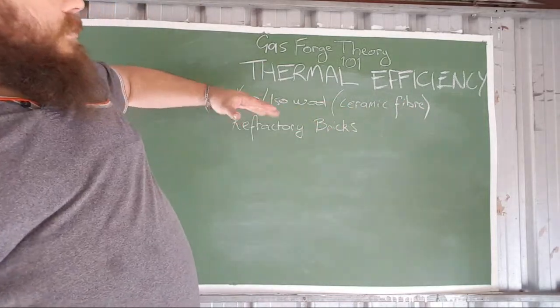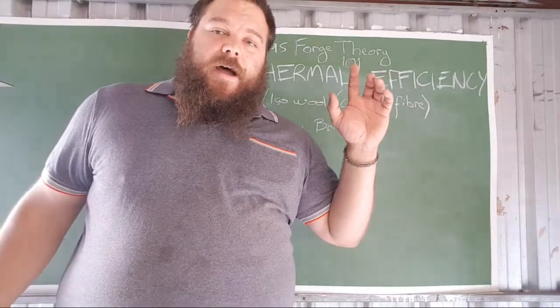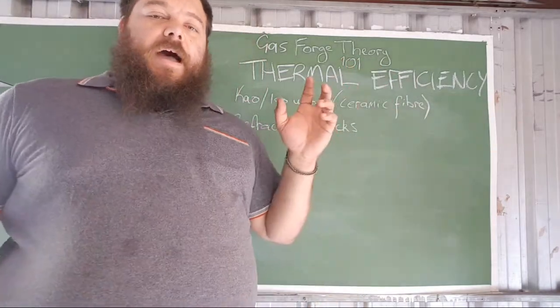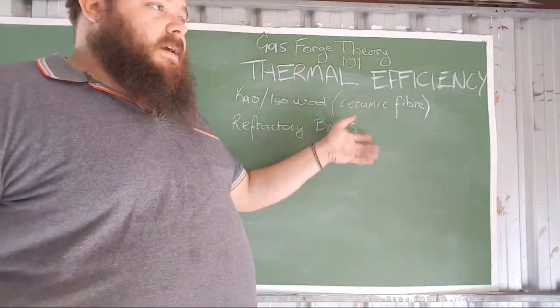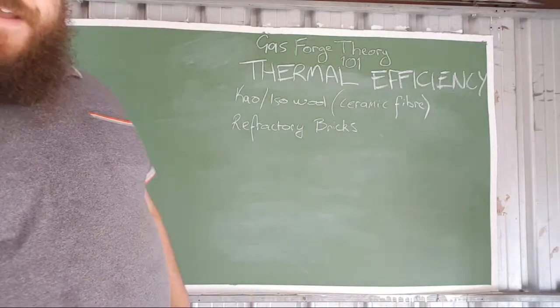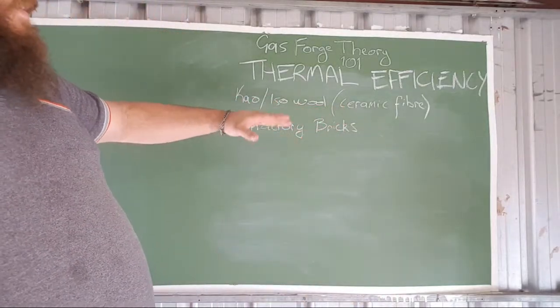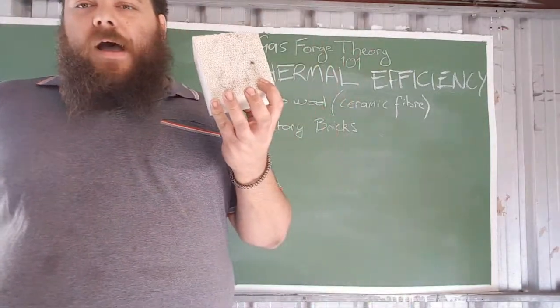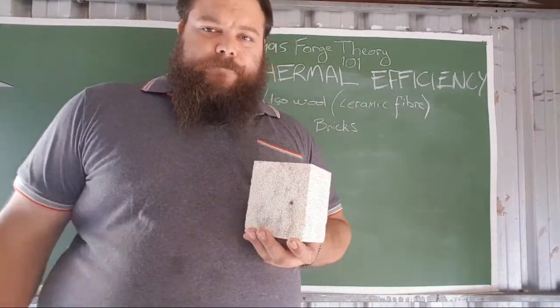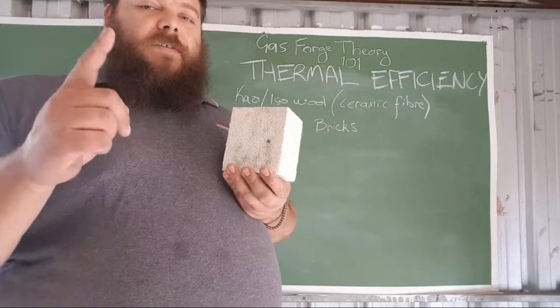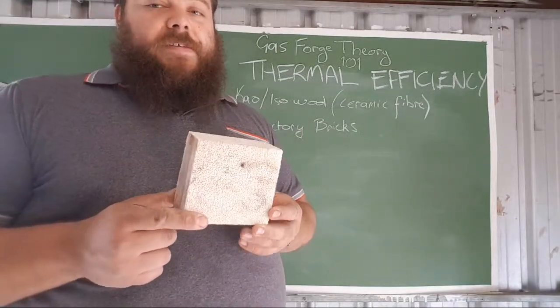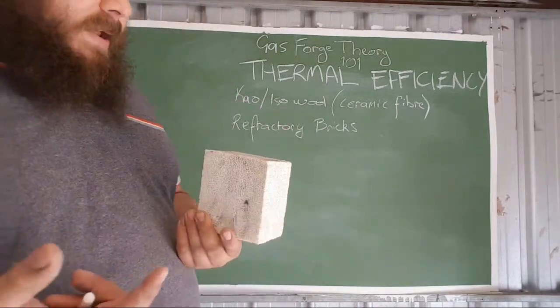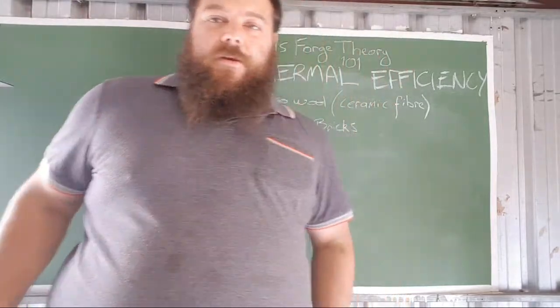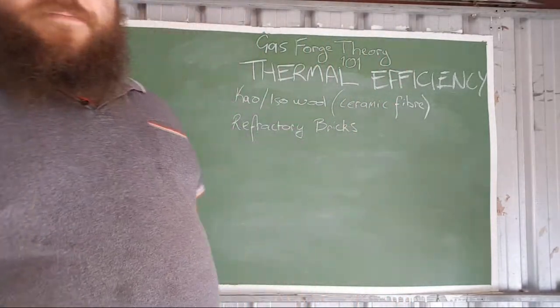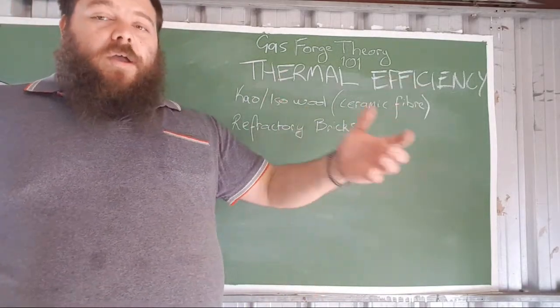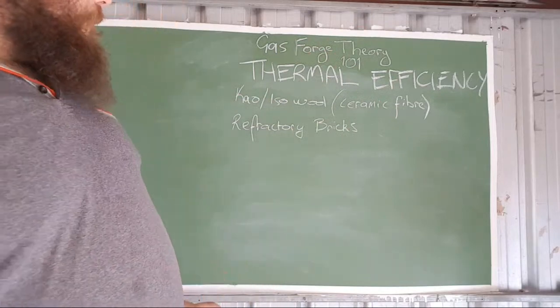So, both Kaowool or ceramic fiber blanket and refractory bricks can have high density and low density variants, with high and low refractive indexes as they go up and down in density. You also have the ability of a low density refractory brick to have a lower heat resistance. Hebel blocks are a great example of a low density brick that has a low heat resistance, but has a decent refractive index. Hebel blocks can break down quite badly under heat. They can also explode if they're improperly manufactured, because Hebel blocks aren't actually manufactured for heat resistance. They do, but they're basically concrete, so you've got to be careful.